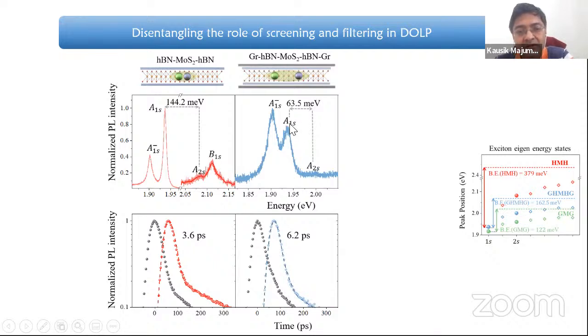We found out that the 2s to 1s separation came down to about 63 millielectron volt. Our Bethe-Salpeter equation predicted that the corresponding binding energy is about 162 millielectron volt. So the binding energy is actually going down very significantly, which means the electron and hole are being separated apart physically in real space. And you also notice that the lifetime has increased, and that also makes sense because your oscillator strength is going down, right?